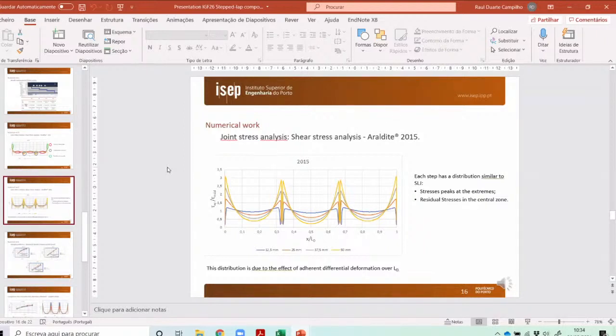For the other two adhesives, since they have some ductility, when these peak stresses are reached at the step edges, plasticization begins until, in the limit, we will have a constant stress in the step. So we can have an increase of strength which is almost linear with the overlap length because of the ductility of the adhesive.